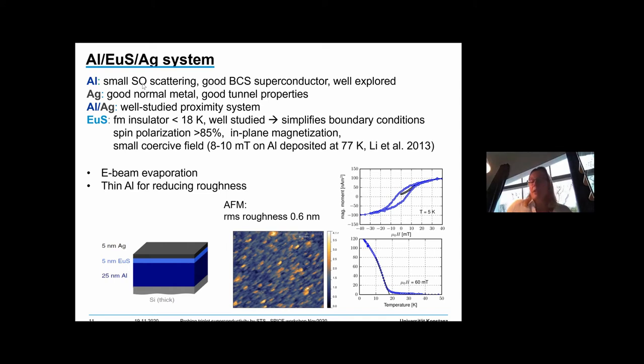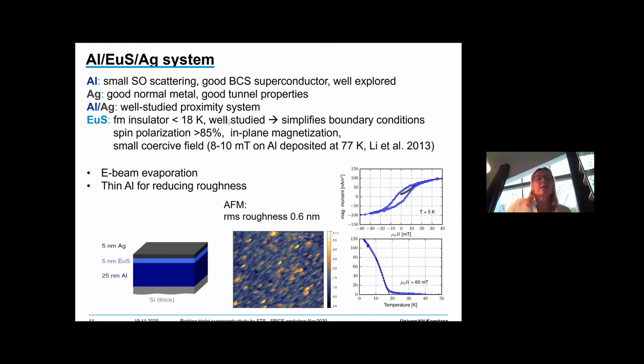We take aluminum because it has small spin-orbit scattering and, to my knowledge, is the only metal that really fulfills BCS theory to a high extent. We take silver as the normal metal because, without UHV conditions, we need clean surfaces — the choice is between gold and silver, and gold is not ideal for the proximity effect in the Usadel equation. Europium sulfide is a ferromagnetic insulator with potentially very high spin polarization — reports up to 85% — and a small coercive field when deposited on aluminum.